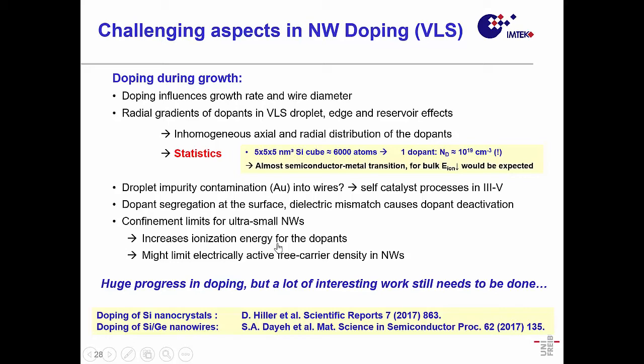And it's also statistical. If you go for these nanocrystals, to just give you an idea, I'm doing this in silicon, and this nanocrystal is 5 nanometer, let's make it simple, a cube of 5 nanometer, then you have one dopant, and that's already 10 to the 19. That would be metallic for bulk, and here you have even then the effect. For bulk, the ionization energy would drastically go down. Here it goes up.